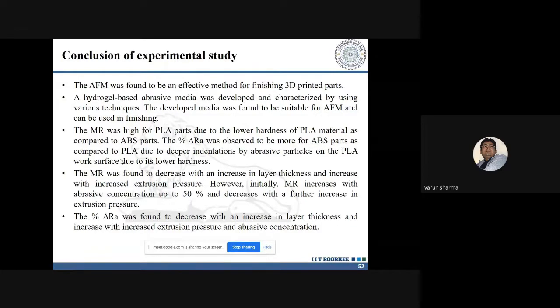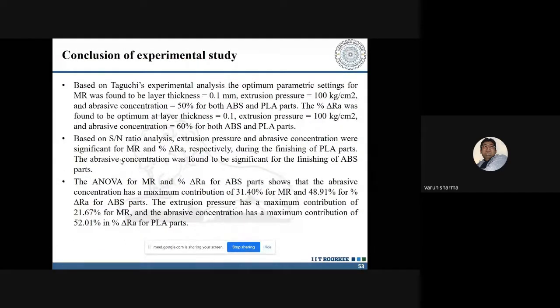EDM you cannot go, you cannot do ECM over here because these are plastic kind of processes. So AFM is the most promising technique in the near future, which can be used for the finishing of the 3D printed parts. The hydrogel media that we developed for this experimentation was an environmental friendly, rather a sustainable media that we were having, and the Ra and the ABS, we were able to get the desired kind of the surface finish.